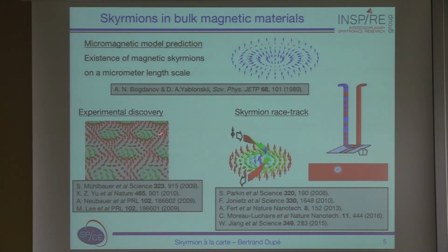They were first seen in these papers. So this is MnSi. They are also seen quite often via Lorentz microscopy. One of the interesting things that you can do with skyrmions is to move them on ferromagnetic thin films, and the idea is to have a racetrack based on isolated skyrmions. As you can see, this is a non-exhaustive set of papers. This is subject to very intense research. You have seen here the anti-skyrmion in addition to the skyrmion.